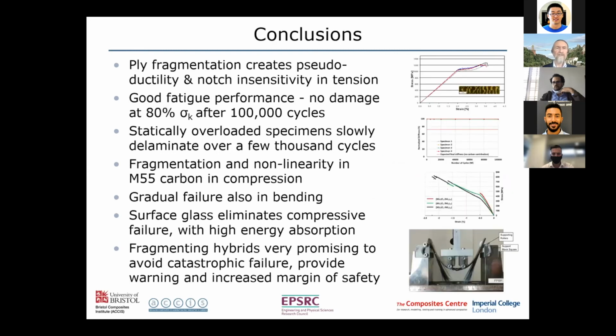So in conclusion, I've shown that the ply fragmentation creates a pseudo-ductile response and gives us notch insensitivity in tension. We have very good fatigue performance, no damage if we keep below 80% even after 100,000 cycles. And if we do statically overload those specimens, they will slowly delaminate, but only over quite a large number of a few thousand cycles.